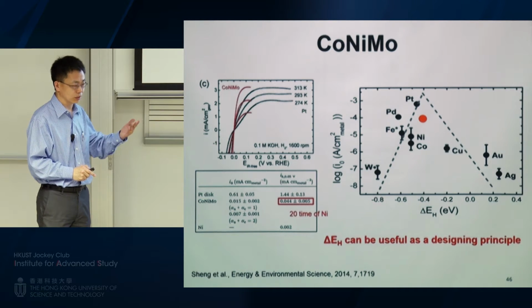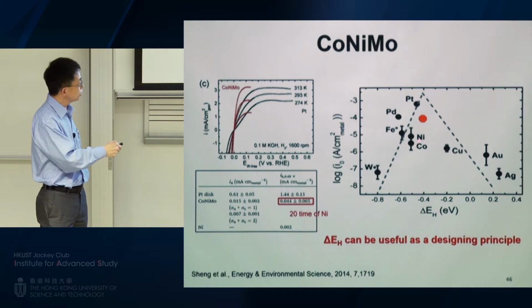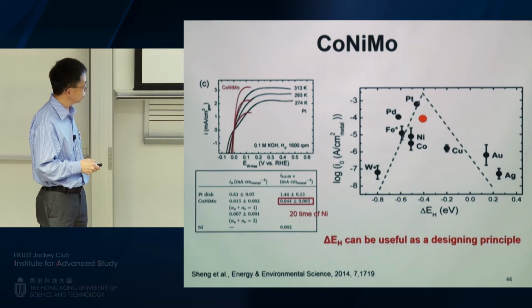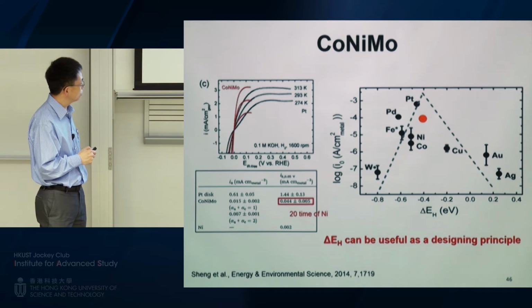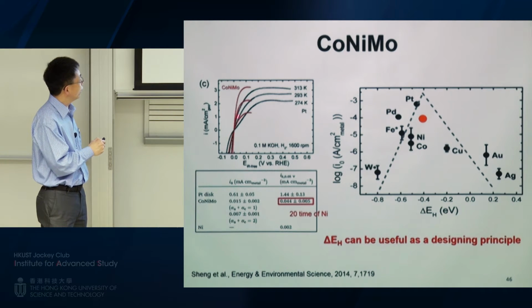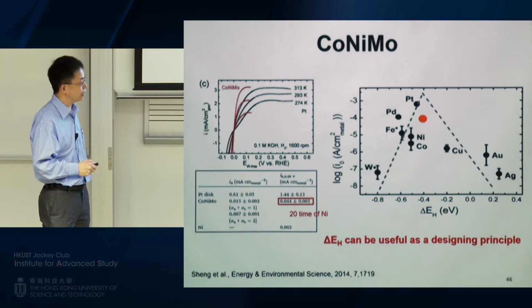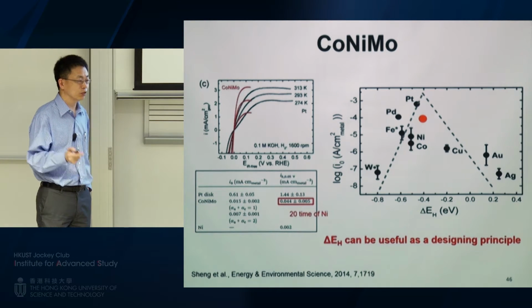But we can increase the loading. So you can see this indeed moved up. But the point I want to make here is, we had a lot of trouble making this nickel cobalt moly catalyst using wet chemistry, which just couldn't reduce these things very nicely.